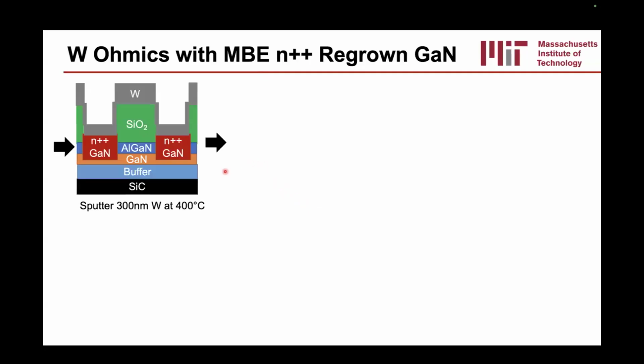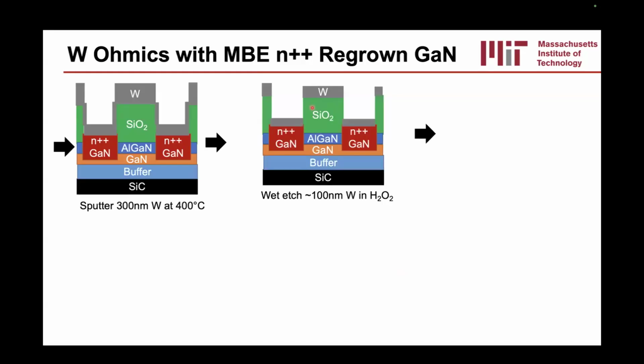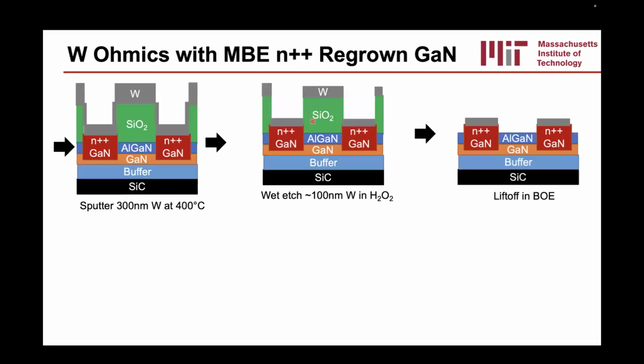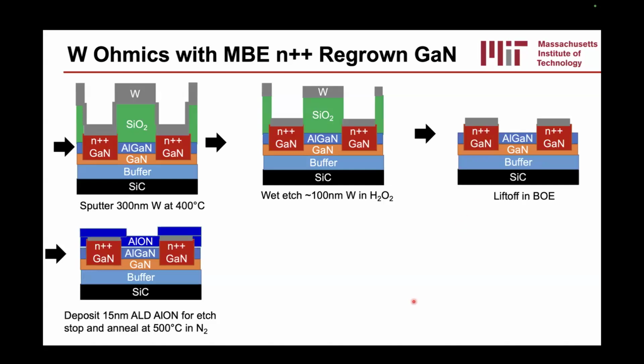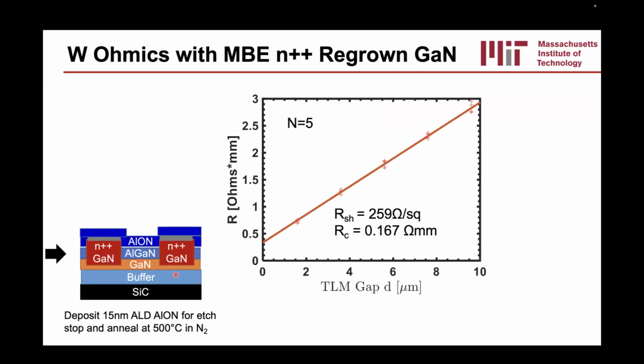Subsequently, we can then sputter tungsten all over the sample here, and we can isotropically etch some of the tungsten in peroxide to remove some of these sidewalls here. And then we can actually lift everything off in BOE so that we have basically a self-aligned tungsten refractory ohmic process. Afterwards, we can deposit our etch stop layer, the ALD aluminum oxynitride, and then we can also deposit pads and do the mesa etch. And from here, we can actually